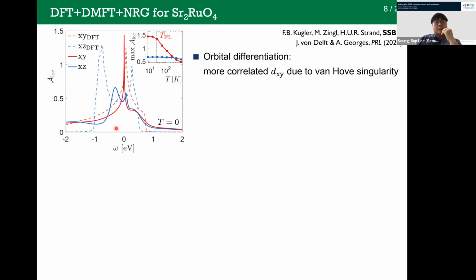It is somehow surprising because in the beginning, the XY orbital had a wider bandwidth, meaning that it has larger kinetic energy, while we chose to use the same interaction parameters for all the 3 orbitals. So it means that the ratio of the interaction to kinetic energy was smaller for the XY orbital. So this simple argument doesn't hold in this system. And actually, the stronger correlation of the XY orbital was induced by this van Hove singularity near the Fermi level. If it were quite separated, it would not be that important, but being close to the Fermi level, this van Hove singularity made all this magic.